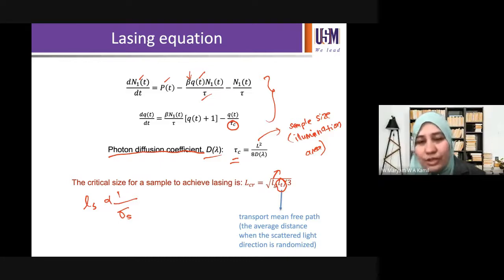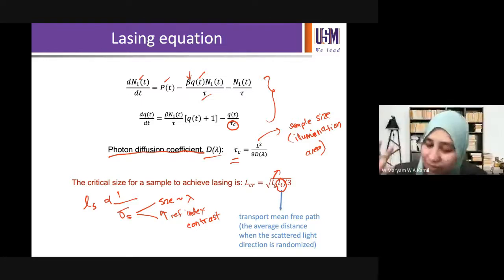Okay, and the scattering cross section, for maximum scattering cross section, you need two things, right? You need to have the size of the scatterer, so the size of the nanoparticle has to be roughly the wavelength of the lasing. Okay, the wavelength, and there has to be a high refractive index contrast. Okay, so the higher this contrast, the better the scattering cross-section is, right? So that's roughly the whole bundle regarding random lasing.